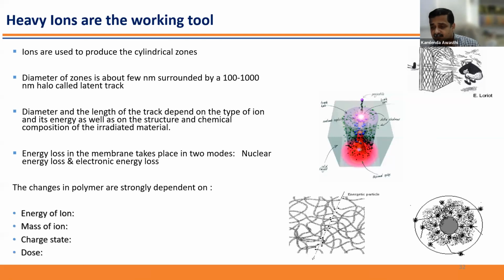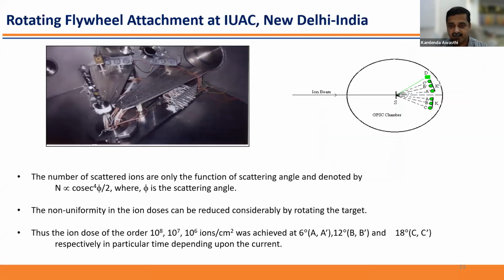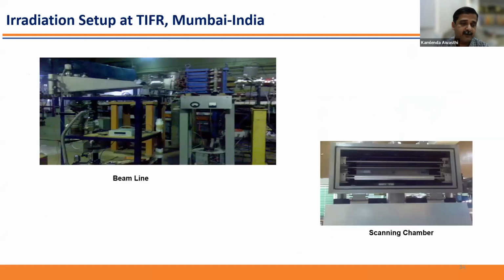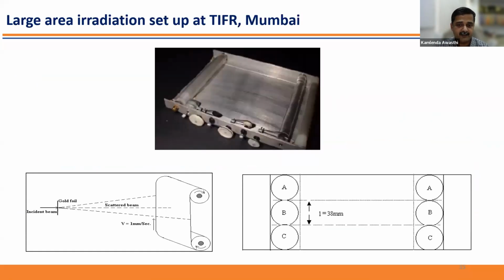So what is happening here, you can see the dark part. This is the path of your beam, and this is the damage created along the track, and this material is basically loosely bound along the track. You can remove it chemically, and you can make the pores cylindrical or conical depending on the size. This is the facility available at IUAC New Delhi and another at TIFR Mumbai, where you can do this kind of experiment for large area irradiation.